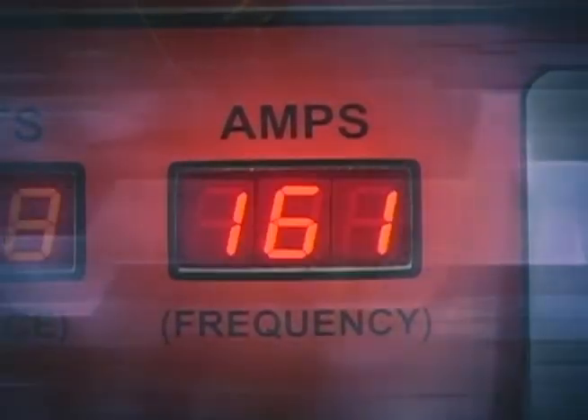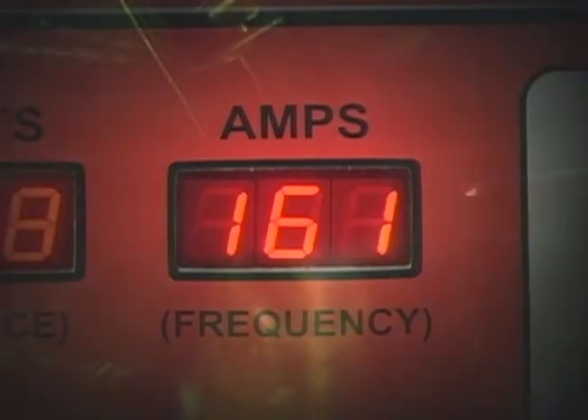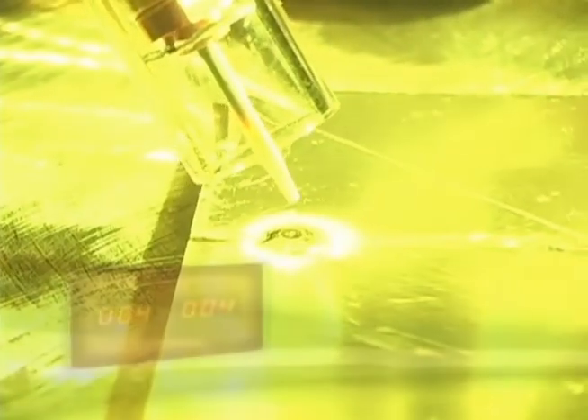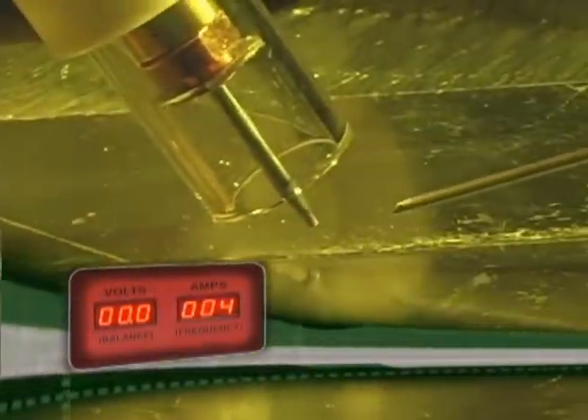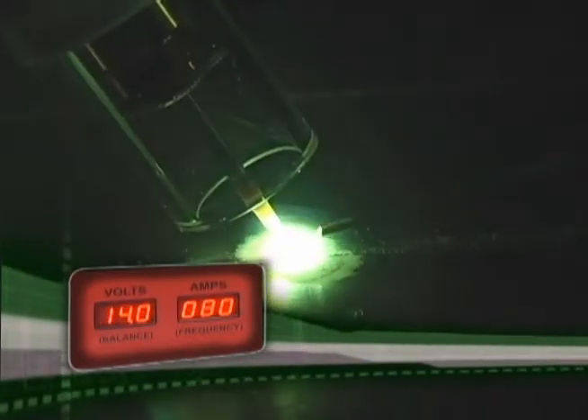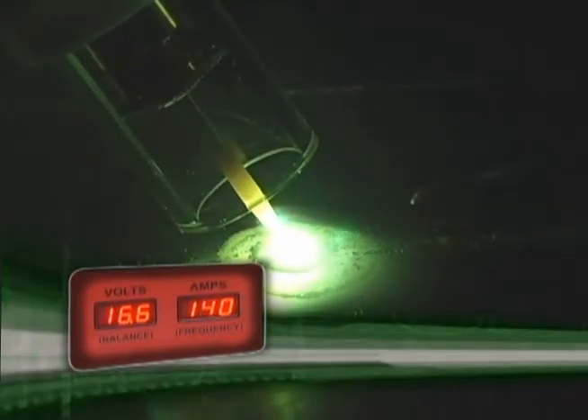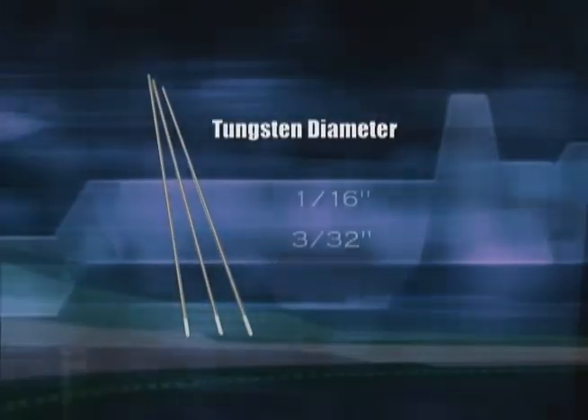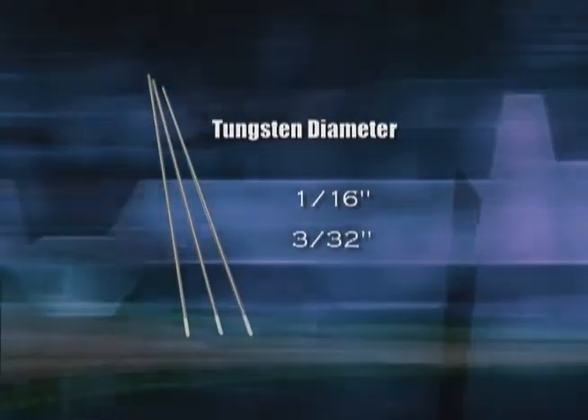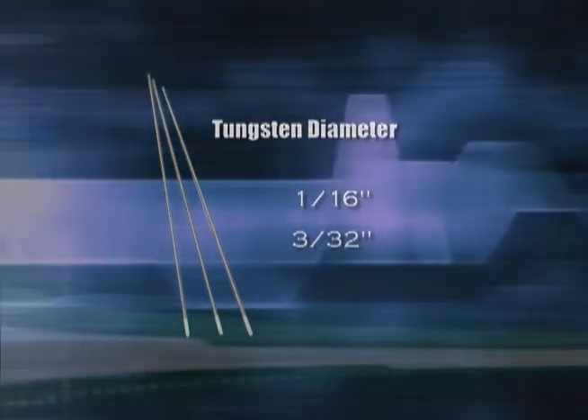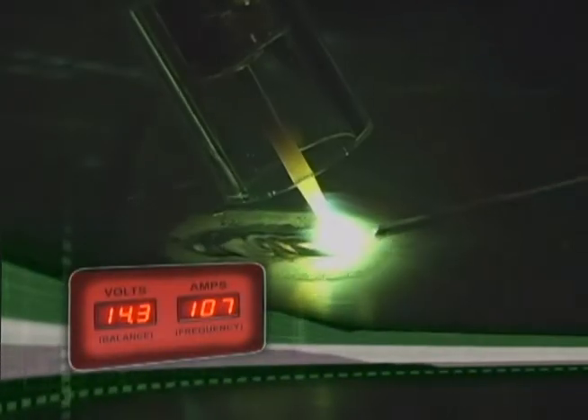We have increased the amperage of the machine to 160 amps to give us the penetration we need in the 1/8 inch aluminum. Also, with aluminum, since we are running in AC and putting more heat into the tungsten, we increase the tungsten diameter from 1/16 to 3/32 of an inch. Other than that, this is just like butt welding thin aluminum.